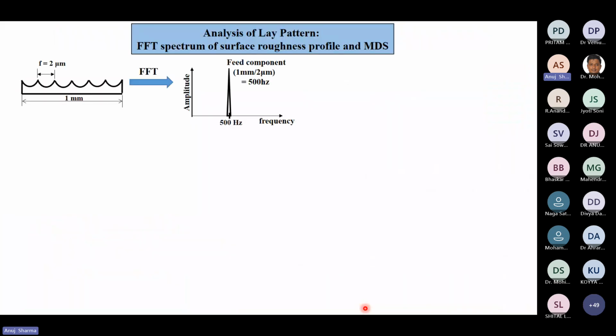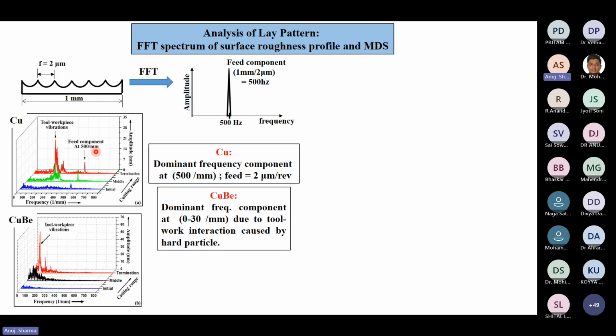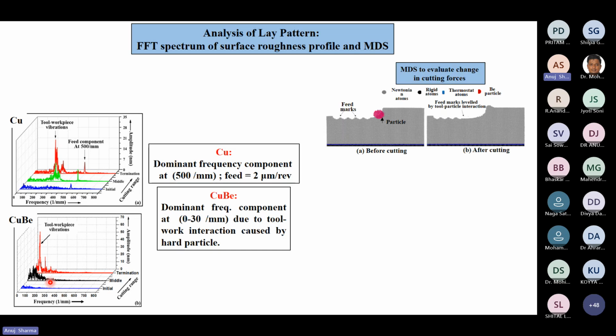So then I carried out FFT, that means fast Fourier transform, which means that if we have 1 mm of surface profile, and if the feed marks are of 2 micron, then the peak will be observed in the 500 Hertz frequency region. For the copper surface, these 500 frequency marks were obtained, but in the case of copper beryllium, there were no 500 frequency marks. That means those feed marks were not there, and there were dominant frequencies obtained. Those components were basically between 0 to 30 per mm. So these are very low frequency components. So what could be the reason for that?